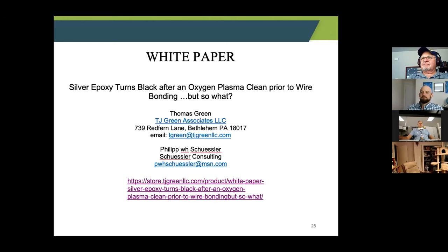But, you know, and then you could also look at a mixed bottle. When I was in Philadelphia at Martin Marietta at the time, later Lockheed Valley Forge, we used to use a mixed bottle, like 3% oxygen and argon, or maybe even 90-10, or just incorporate the oxygen with the argon. But the argon is just knocking atoms around.